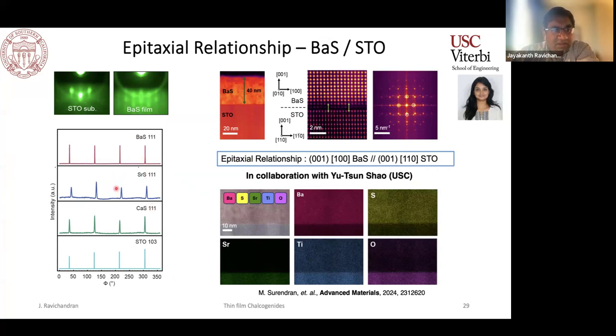And we do get a very good epitaxial relationship between our substrate and your film, all the way from calcium sulfide to barium sulfide, with barium sulfide seeming to have the highest quality. And presumably, even in the stability sense, barium sulfide is much more stable than the other alkaline chalcogenide materials.